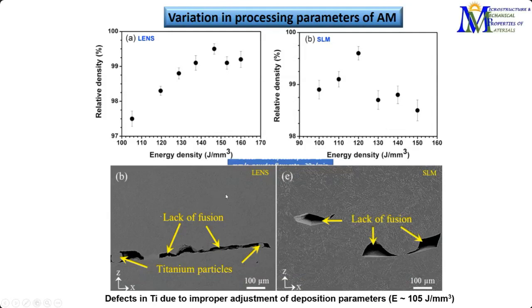This is LENS versus SLM, showing the defects that are formed. You can see there is a lack of fusion that leads to crack generation, cracks more than 100 micrometers in size, and these are completely bad news for any application requiring cyclic loading, or even for normal tensile purposes. If we end up having something like this, that component is of no use.